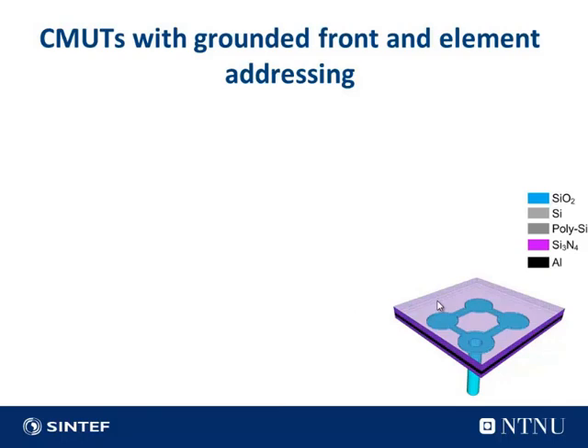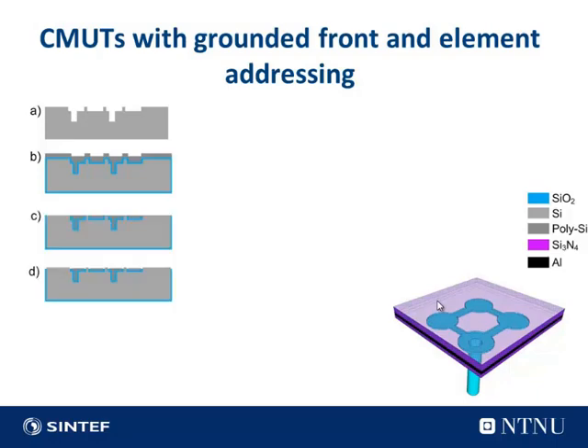So I'll just guide you through the processing and just show first the simple design of one element. It is the 2 by 2 membranes and the polysilicon, the via, and the triple stack membrane. So we start with a 2-layer, or 2-mask, reactive ion etch process to create the bottom electrodes and the vias. And we grow isolating oxide and fill them with polysilicon. And the polysilicon is doped. Then we do a CMP process to get a smooth surface, and we do the cavity etch of 60 nanometers, and then we etch down the isolating oxide to change the properties a bit. Then we deposit LPCVD nitride, that is to be the membrane, on a different wafer.